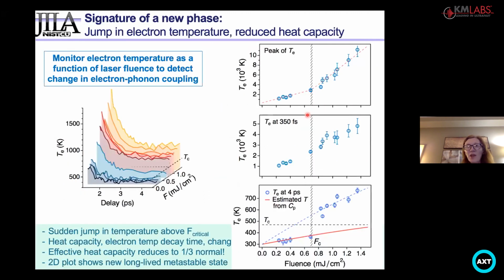And to see what that was, we used time-resolved ARPES to map out the electron temperature as a function of time. And we found this very curious behavior that as we heated the material with higher and higher laser fluence and looked at what the electron temperature was at different times, what we would see is that at a certain fluence, the electron temperature would suddenly jump. And in this case, by hundreds of degrees Kelvin, as we increase the laser fluence.